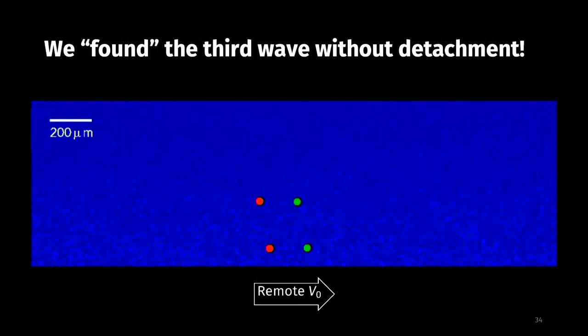Now, the experiments I showed you didn't reveal this particular Rayleigh wave speed crack. They showed you two waves going in opposite directions, both with detachment and so on. But if you probe reasonably carefully and play around with the parameters a bit, you can, within quotes, see the other wave. Now there's no detachment, so you have to put in cross polarizers and do photoelasticity and recover the stress field, but you can see the signature of that in the experiments.